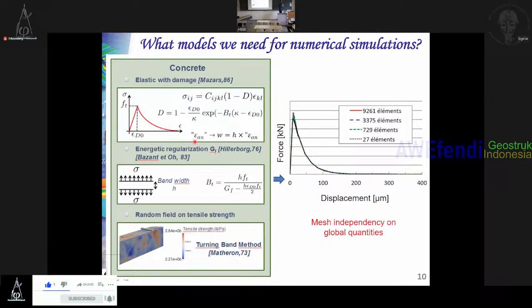Normally it's not an anelastic strain because it's an elastic damage model, but it can be used in order to estimate the crack opening. So you multiply this anelastic strain by the size of the element. And if you do this type of numerical simulation, you will see that your results will be mesh independent.